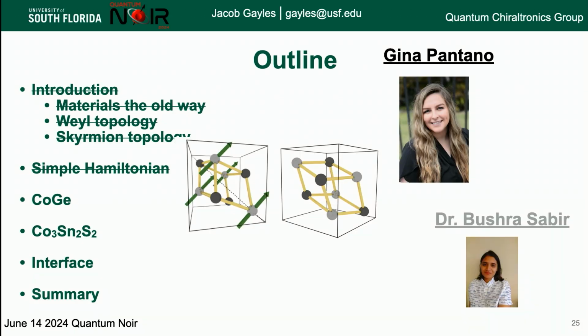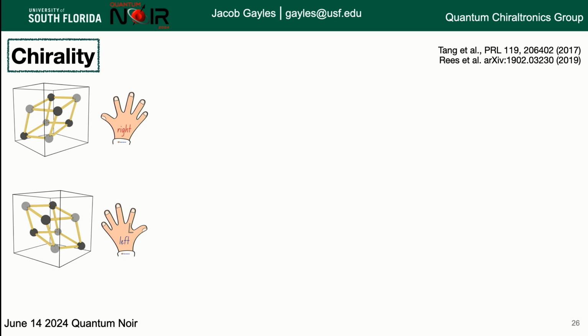Okay, good. So now let's go to some of the results of the students. This is a student on a Fulbright in Germany, and also a previous postdoc here, where we looked at these chiral compounds, which I'm going to explain shortly. So in here, what we have looked at are these crystals called B20 compounds, whose crystal structure inherently has a chirality. It has a left-handed and right-handed chirality, just like DNA. And that chirality imprints onto all of my properties, such as my exchange, my DMI, my Weyl semimetal. When it's non-magnetic, I get one of the best Weyl semimetals that we've found, yeah?